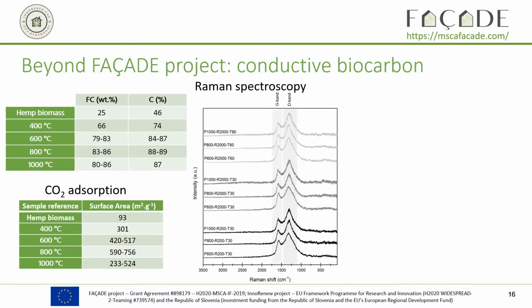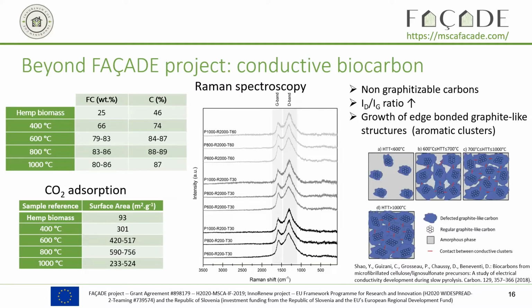Then we looked at the microstructure of the biochar using Raman spectroscopy. And with the Raman spectroscopy, we didn't see any order of the structure until 400 degrees. But then from 600 degrees and higher temperature, we started to see these G band and D band that are characteristic of highly ordered structures.